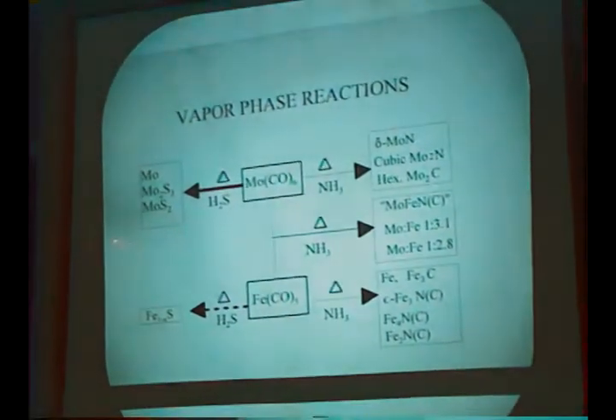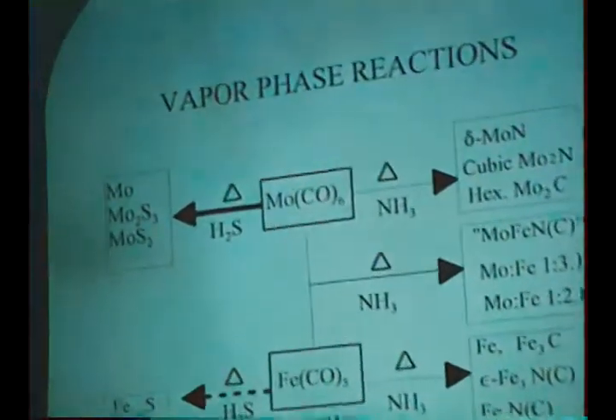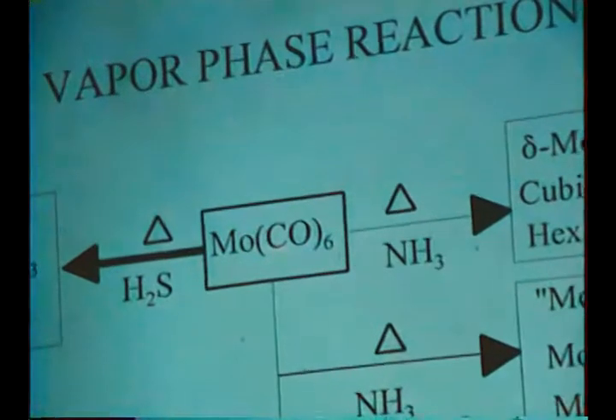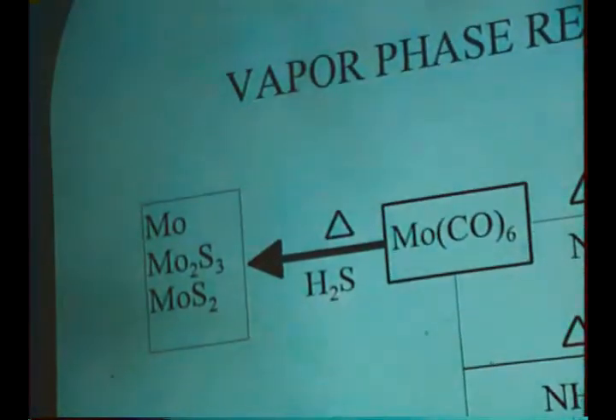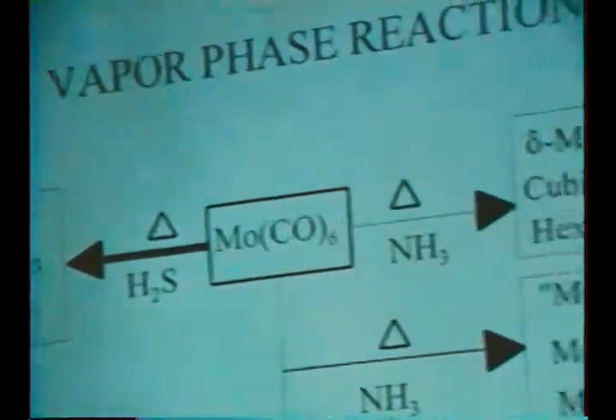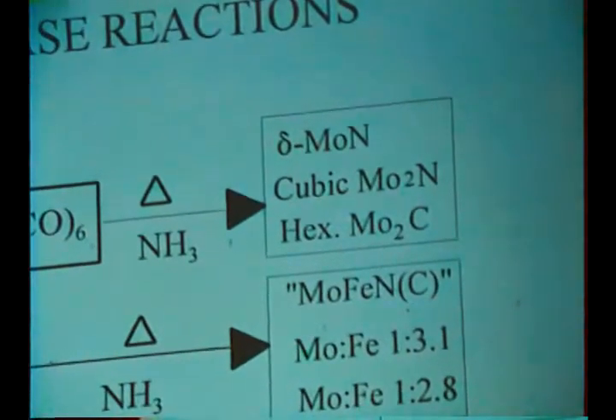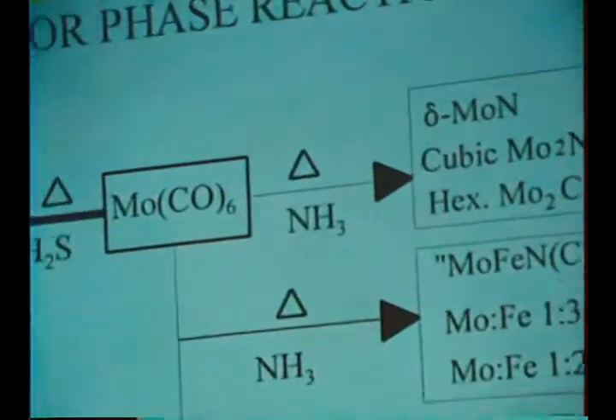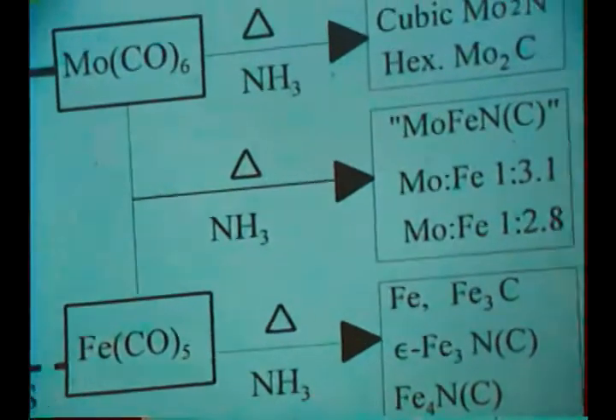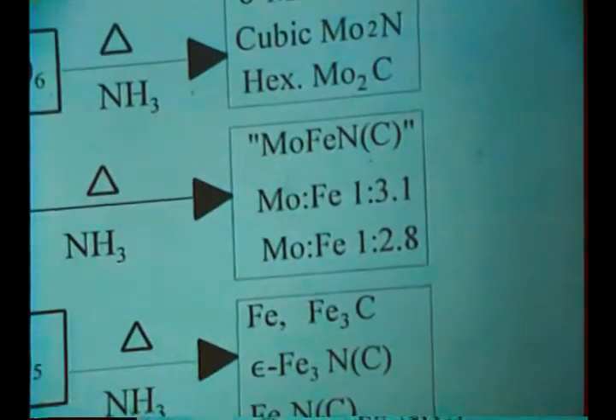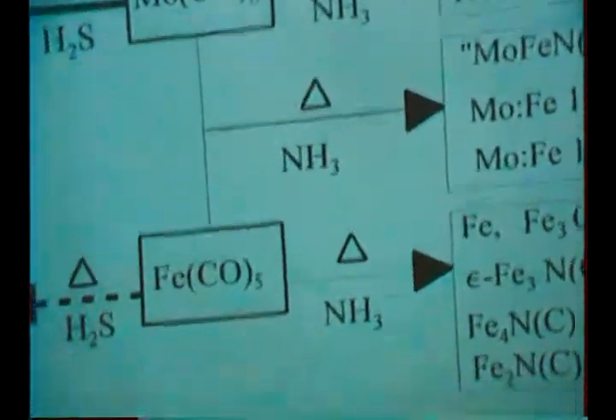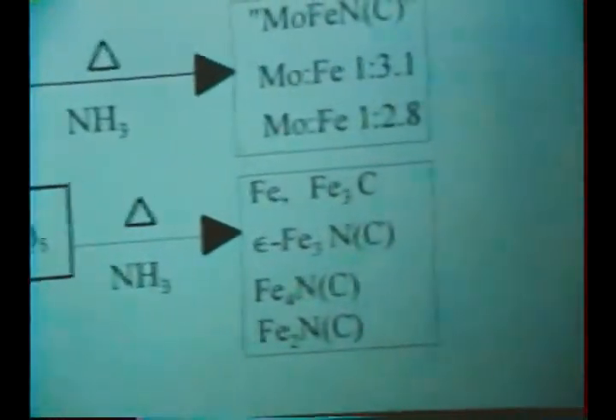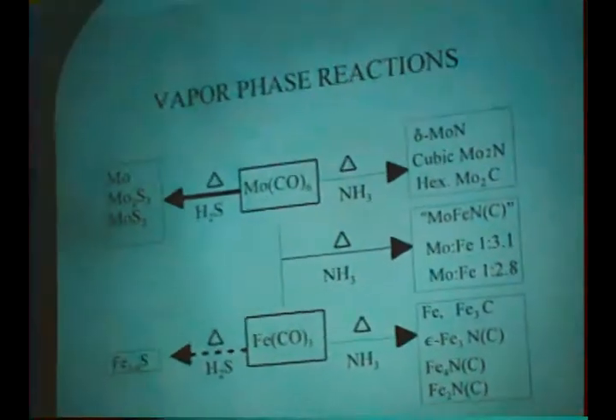This is basically an overview of the materials that can be made with this vapor phase approach. Starting from molybdenum hexacarbonyl, reacting that with hydrogen sulfide, both in the vapor phase, could make molybdenum metal very easily. Mo2S3 can be made with the reduced molybdenum phase, and MoS2 can also be produced with this reaction. Going the other way, the molybdenum carbonyl reacted with ammonia produces a variety of materials.